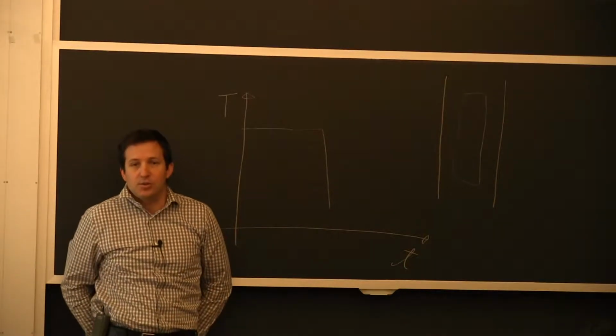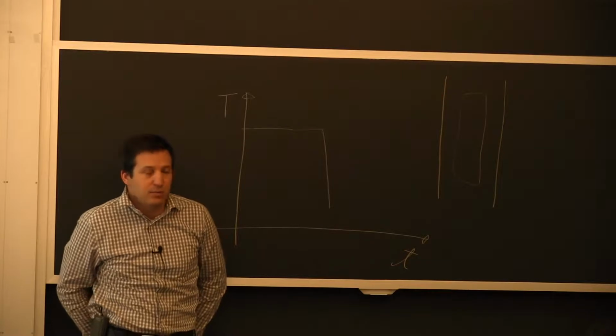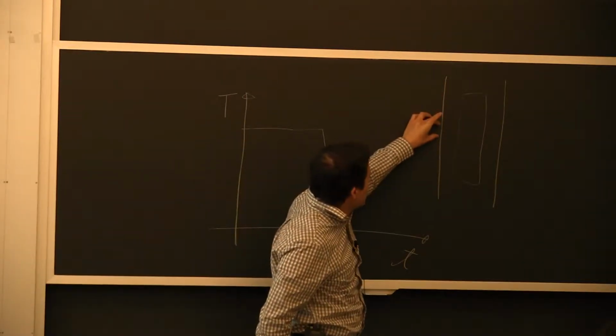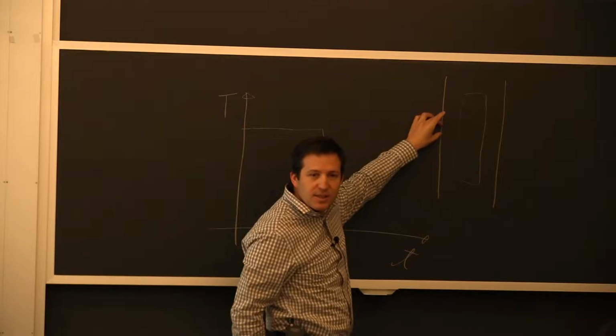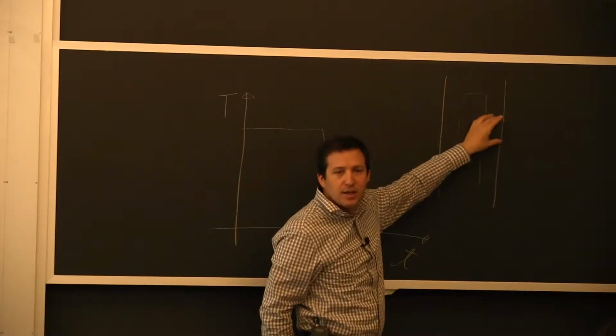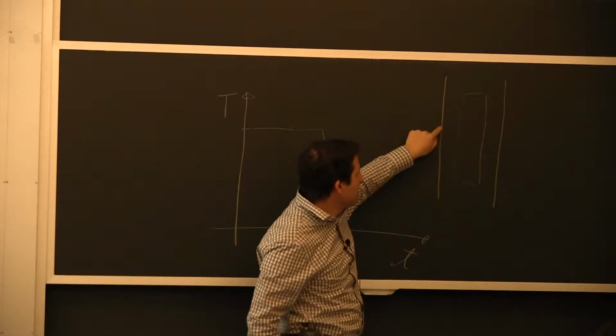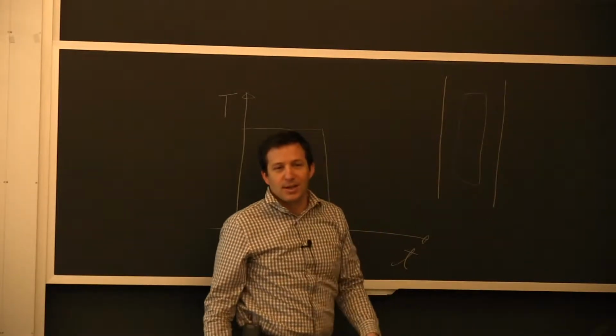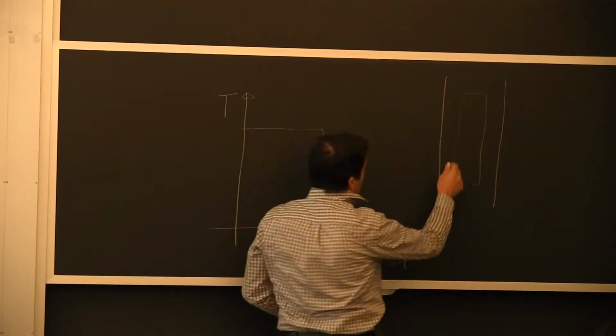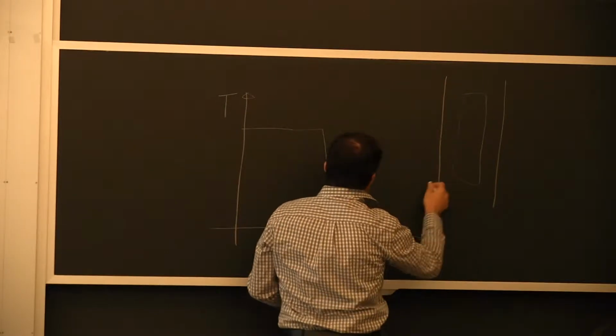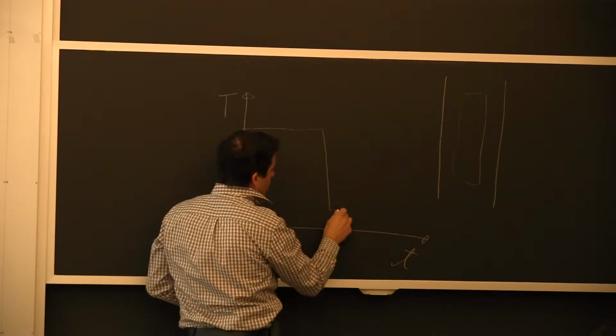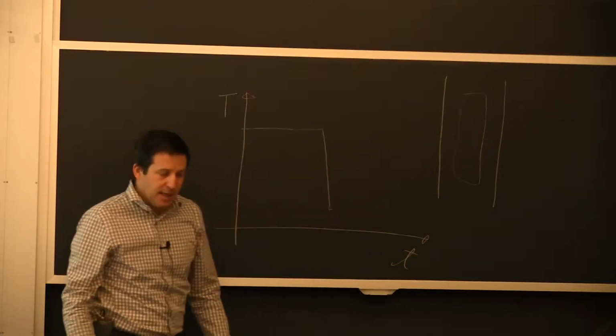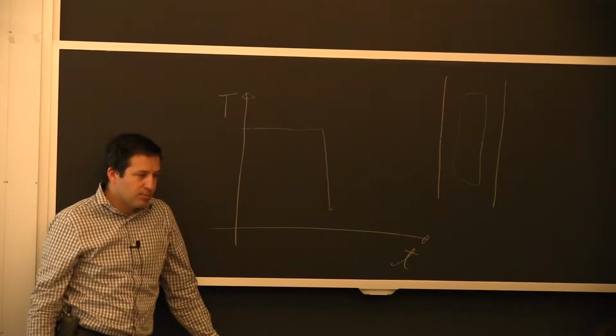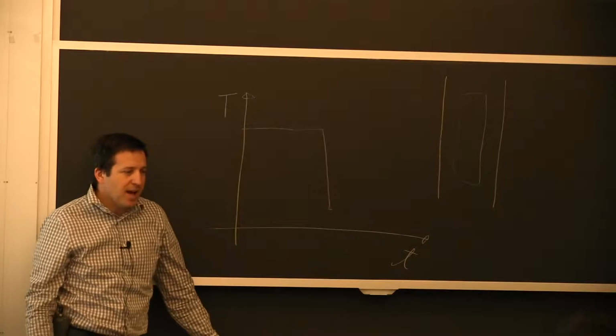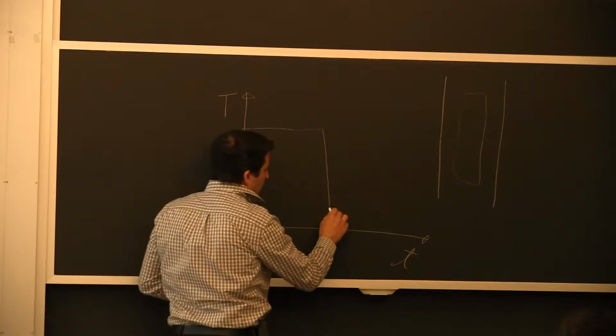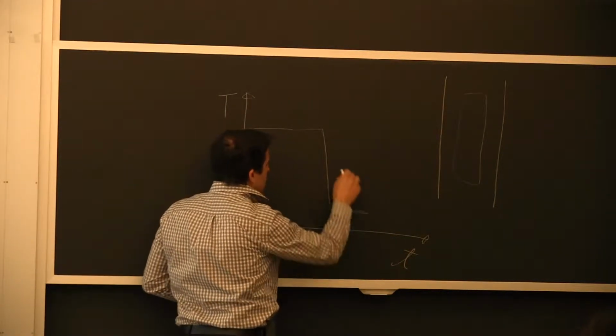It's the same way that you do tempered glass. You cool it down rapidly, and you deform plastically. You exceed the yield strength on the surface on each side, and when everything cools down, you're left with compression, tension, compression. It could be good or it could be bad. It depends on your application. So in the end product here, once you're quenched, you have these residual stresses. Now, you could use the alloy as is in this quench condition, but it's normally very soft